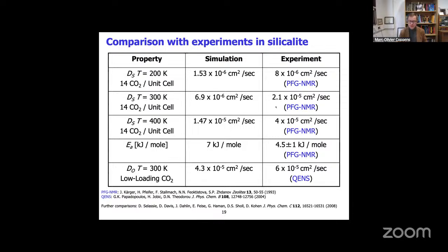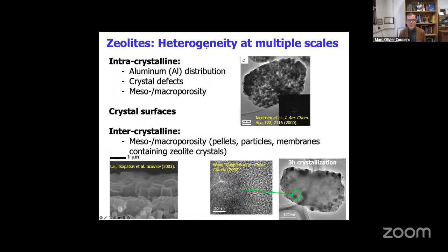in many situations and a much better understanding, especially for quite well-defined materials, such as this ZSM-5 or the silicalite, especially if we have very good samples and we can compare them with simulations where we can go across these length scales. But even for zeolites, these microporous materials, there may be heterogeneity, which is beyond the chemical heterogeneity. There are defects, there are meso and macroporosity in it, either on the inside or outside. In fact, controlling this porosity is extremely important if we want to create membranes, as in the elegant work of Michael Tsapatsis and colleagues, because the larger pores in between may otherwise control the transport. And the barriers in between these crystals, both in catalysis and in membrane operations, may actually dominate the overall transport. So these surface barriers have become an area of great interest.